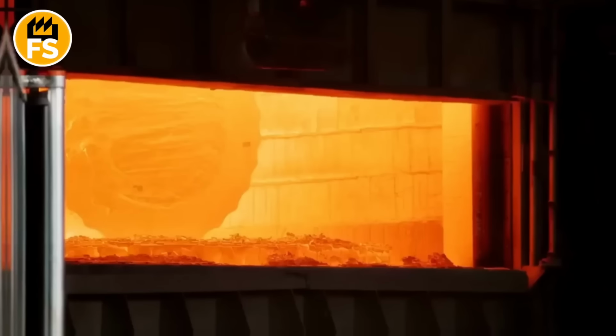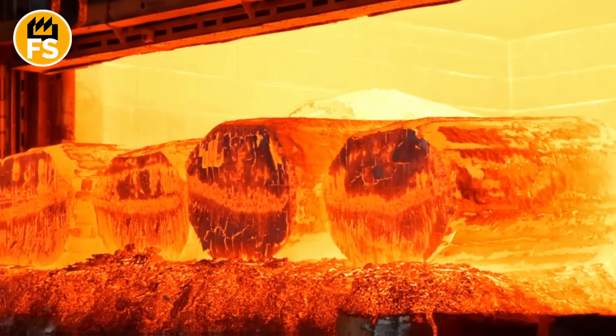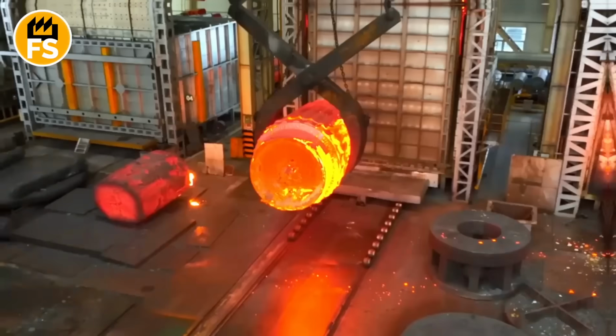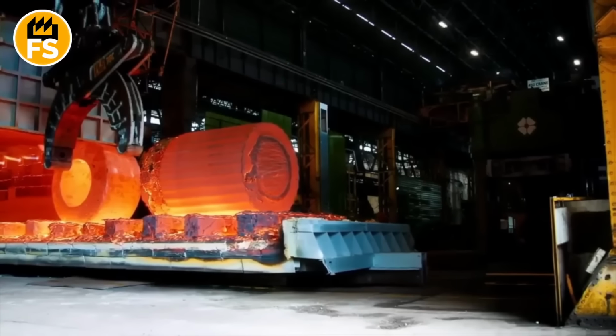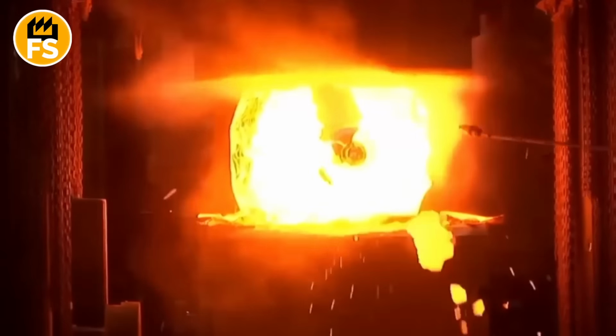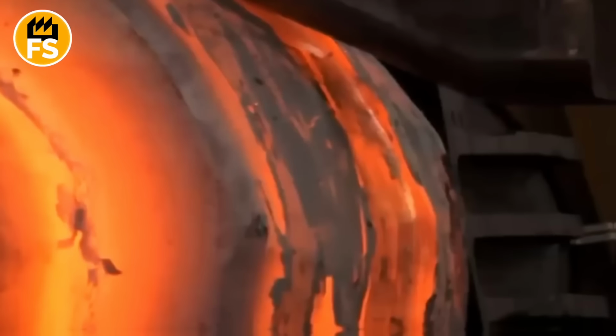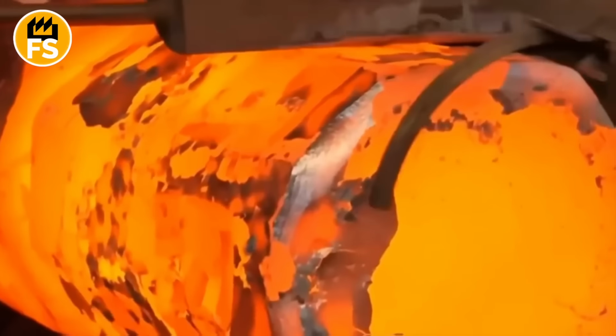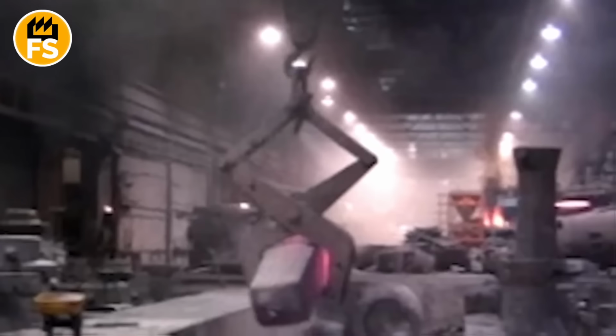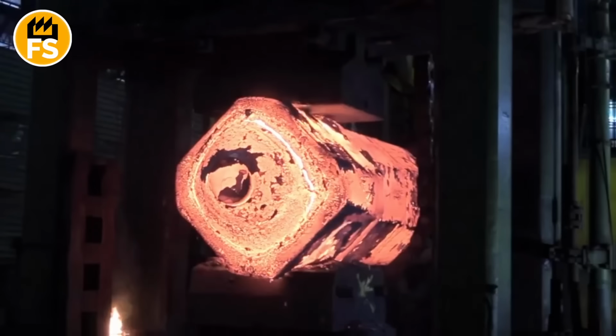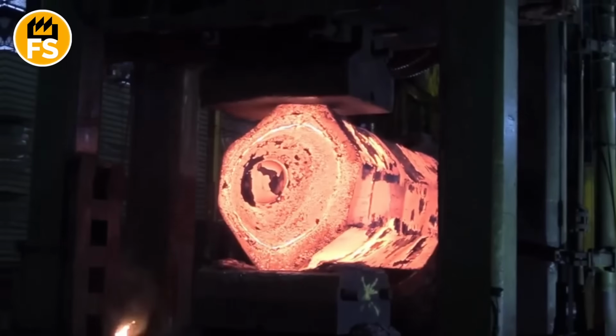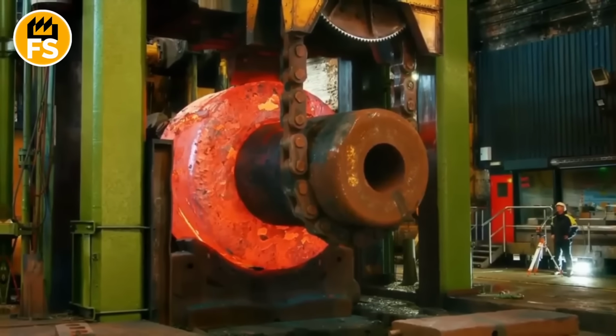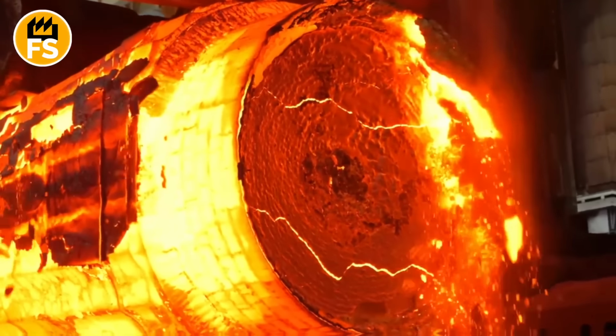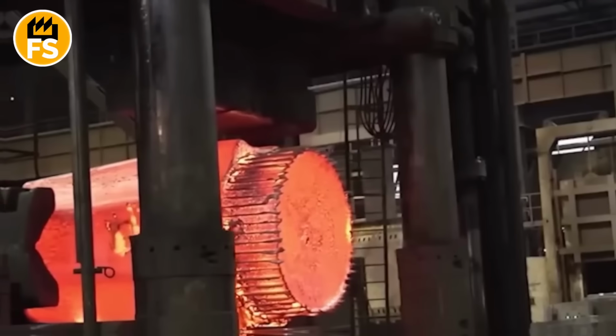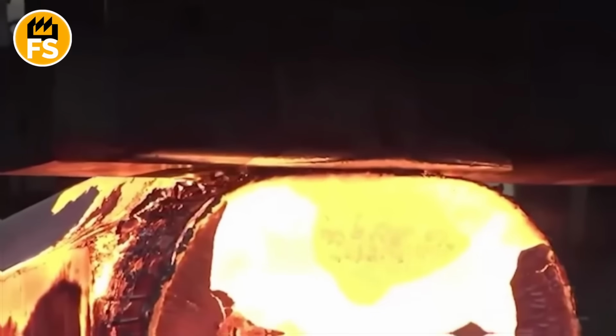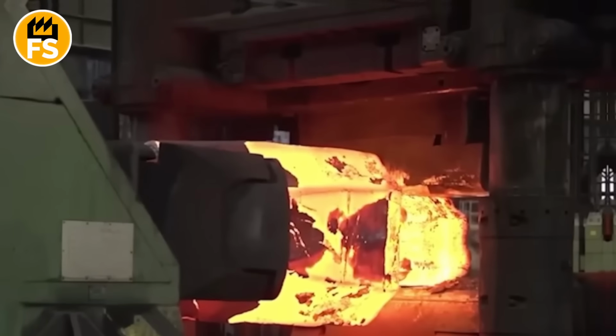Before forging, the ingot is again carefully heated in specialized furnaces. This process can take weeks to guarantee uniform heating throughout the entire volume of metal. The forging itself is done on giant hydraulic presses capable of creating pressure in the tens of thousands of tons. The press breaks down large, brittle cast crystals. The pressure compresses the metal, eliminating microscopic voids that may have formed during casting. The metal gains a directional fibrous structure, which significantly increases its strength, toughness, and fatigue resistance.